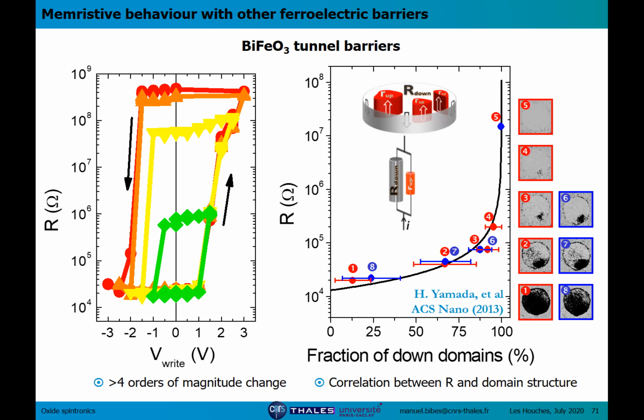This was on barium titanate. A few years later, we did the same kind of experiment with bismuth ferrite. And again, we have the correlation between the domain structure and the resistance.